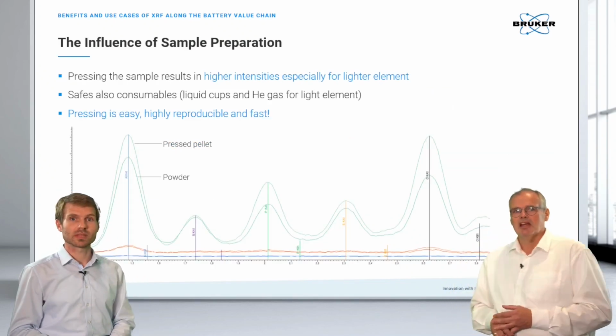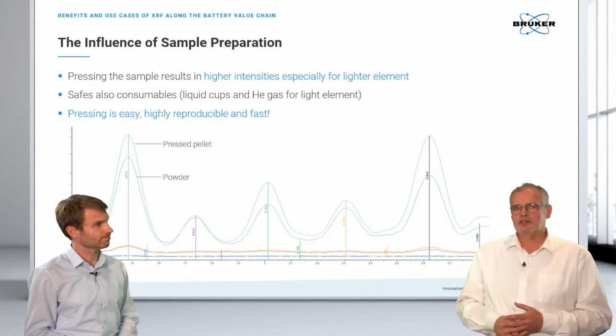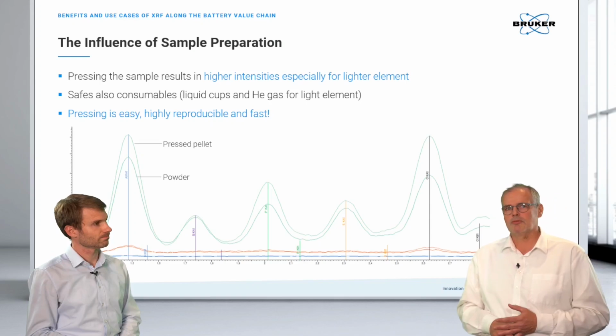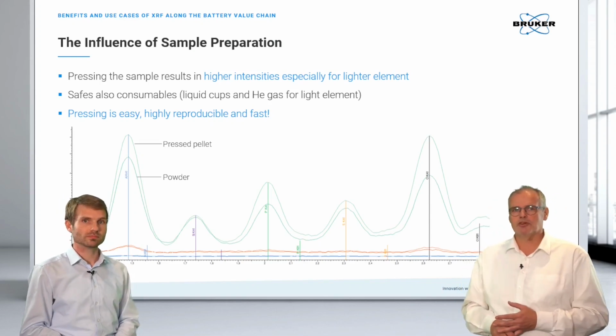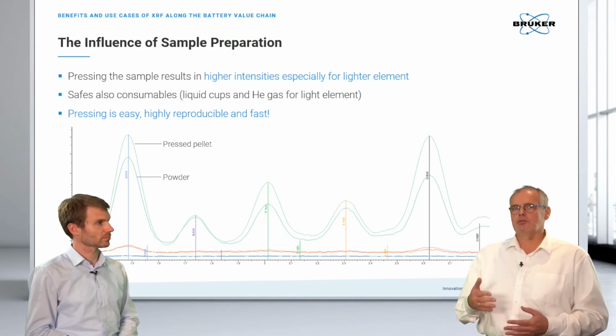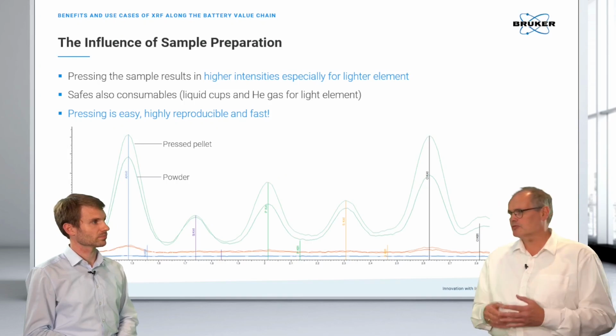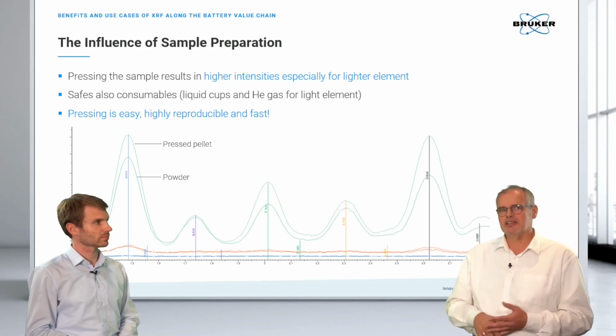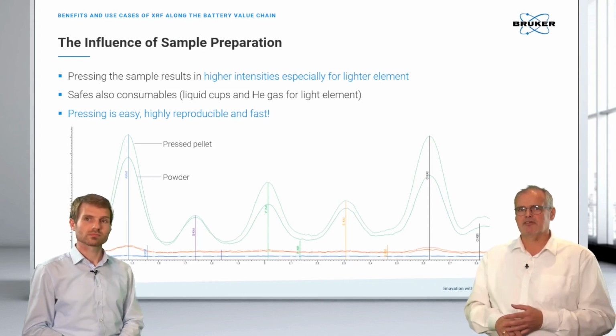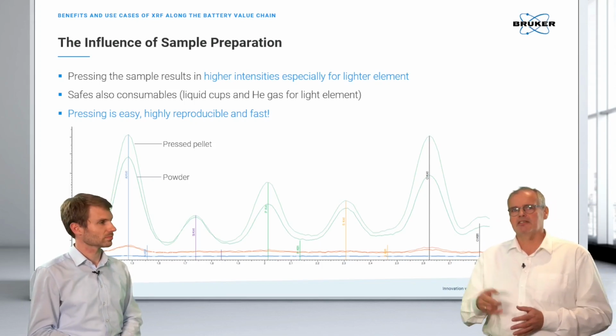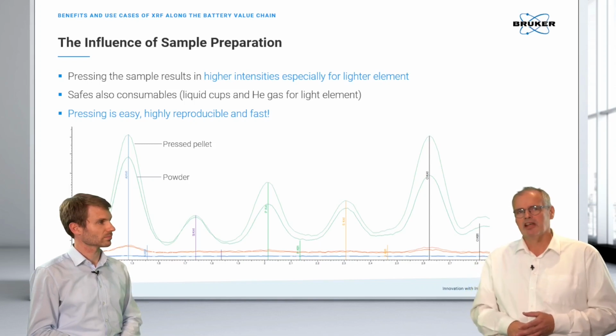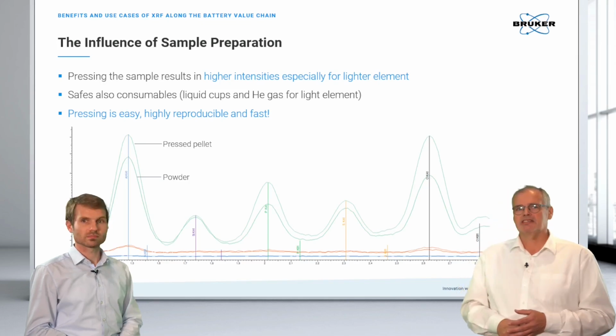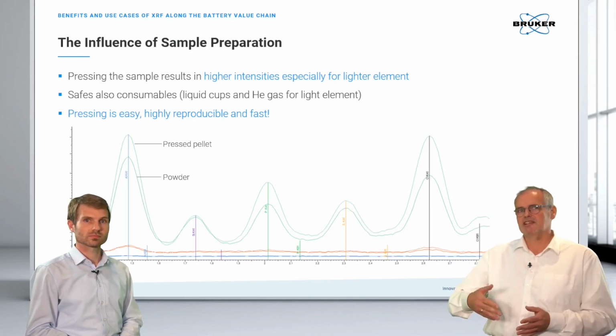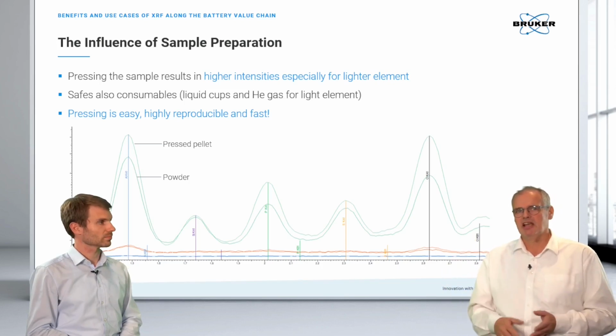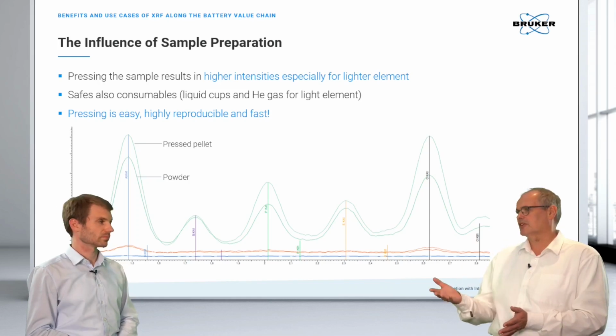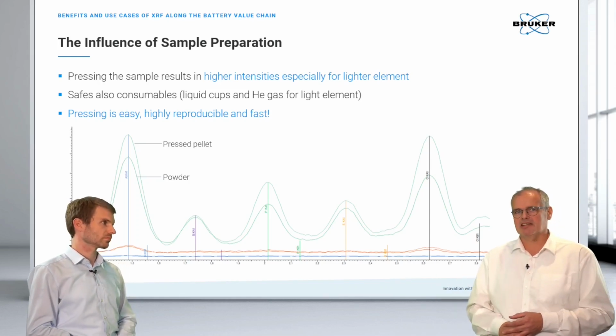Exactly. So then, of course, we talked about the fact that we can work with loose powders, and that's the very straightforward way. In the moment where you receive the material and we want to be a little bit more accurate, with a little bit more precision, it might be useful to press the sample into a stable pellet, which is just an investment of one additional minute. You can see the effect here comparing the two spectra. The lower one is the loose powder, and the top one is the pressed pellet spectrum. There is an additional plus in intensity, because we are compacting the powder and getting rid of the air in between. This leads to a higher intensity.